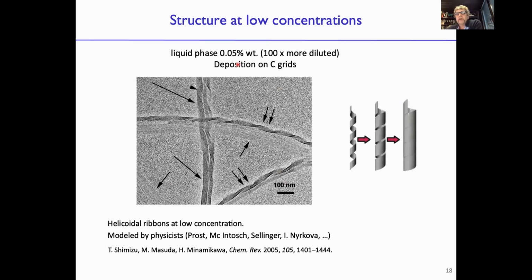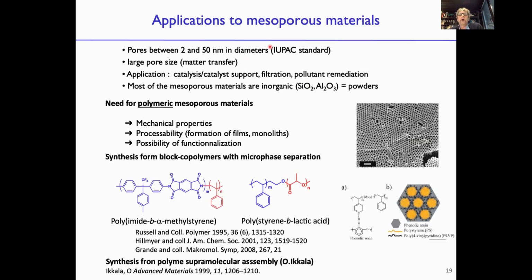At very low concentration, these molecules still self-assemble, but don't form tubes anymore, just helical tapes, like you can see here. And it's 100 times more diluted than the previous image I showed you. So it's in a liquid phase, and it has just been deposited on carbon-coated grids to observe this. It has been shown in the literature already that helical tapes, like in here, are precursors to full nanotubes. And we took advantage of this to use these objects as porogens to make mesoporous materials.